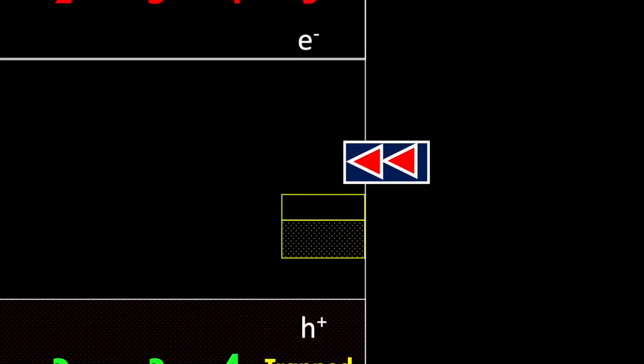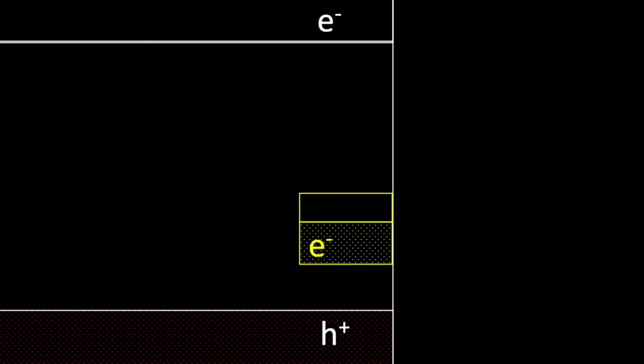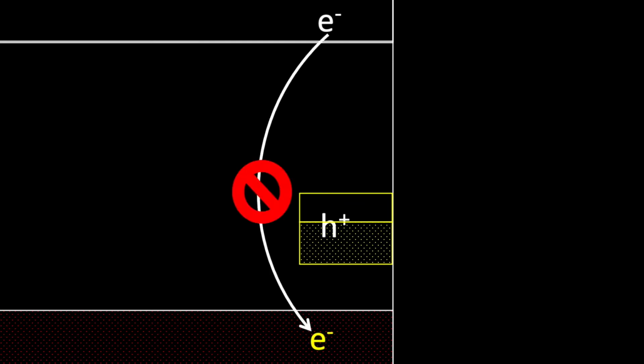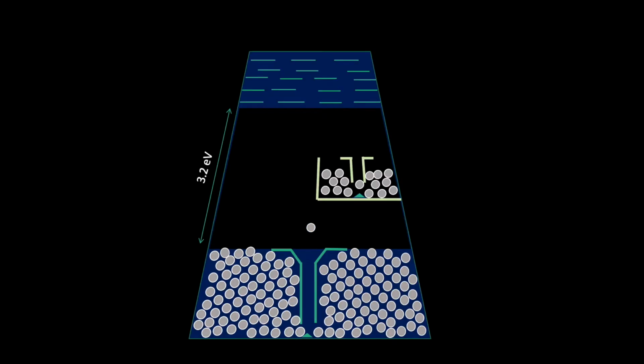If we go back and see it from another angle, the reason behind this observation could be hole entrapment. The limitation of this technique in distinguishing between hole or electron traps makes these claims very speculative. There is also another inconsistency here. To have these states acting as traps, they need to be unoccupied or partially occupied. But previous calculations are showing fully filled electronic states, contradicting with the electron trapping behavior of these states.